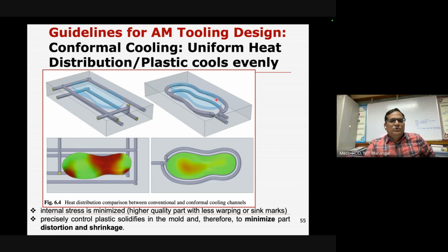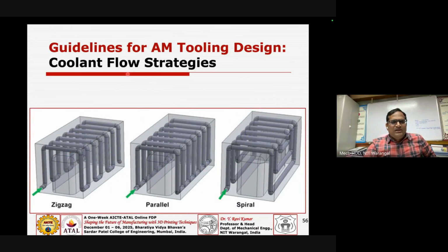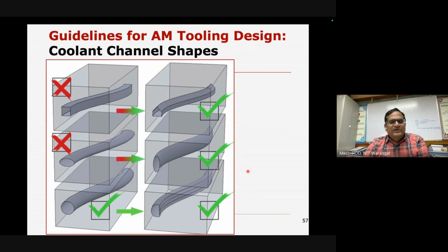Not only this, the tool life has also increased because of these conformal cooling channels. So you can see several design strategies, maybe the pattern of how the coolant will flow, maybe a zigzag, parallel, spiral, and even the cross section of your cooling channel. You have some guidelines to be followed in order to use this more effectively. In the literature, people are trying different cross sections and different patterns in order to improve the cooling efficiency of the tool, right?